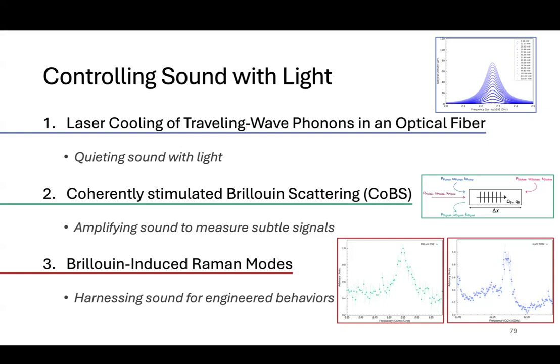Were you ever able to conclude that you were seeing Raman light interference? Yeah, no. So we got close on many different materials, but the lengths that are required are related to the mean phonon travel distance in a given material. So it's different for different materials. For carbon disulfide, the phonons travel an average length of about 5 microns. So we got to 100 microns in carbon disulfide. Far gap to get down to 5. I had a 10 micron cell that I exhaustively tried to measure in, but even we would have to go half of that more.